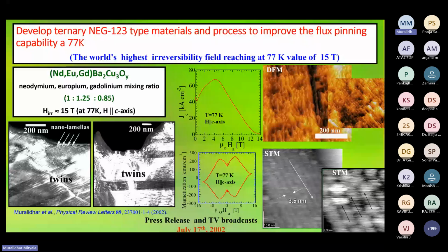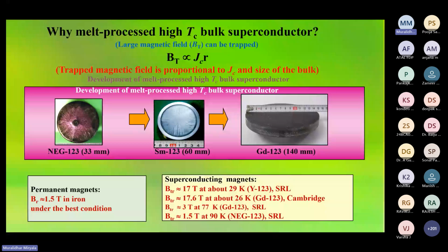We did experiments using TEM, STM scanning tunneling microscopy and more, and estimated the composition at this nanoscale. Eventually we found that LRE-rich clusters form at the nano order. As a result, we made several such materials in large sizes, because the trapped field is proportional to Jc times R, the current carrying capacity times the diameter of the material. We made the world's highest large-size material. As a result, you can see at the bottom, one can make 17.6 Tesla at 26 Kelvin, or even at 90 Kelvin, a very high temperature close to the superconducting transition temperature, one can make 1.5 Tesla.